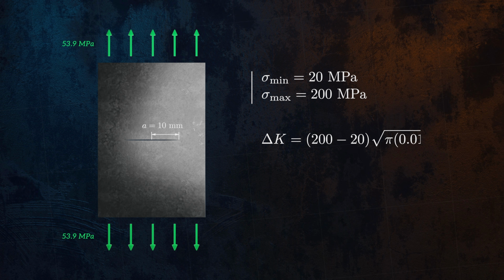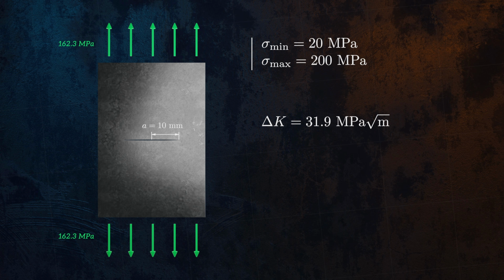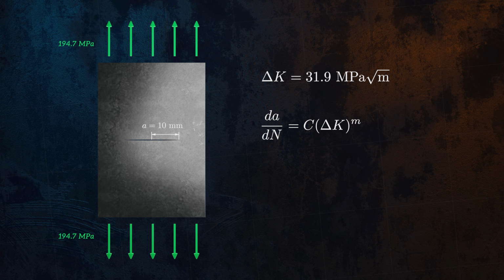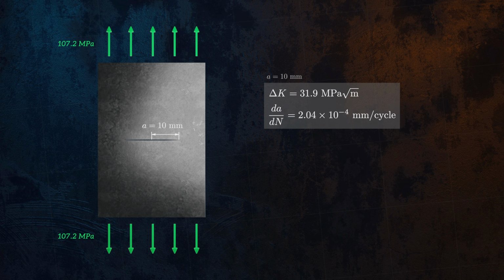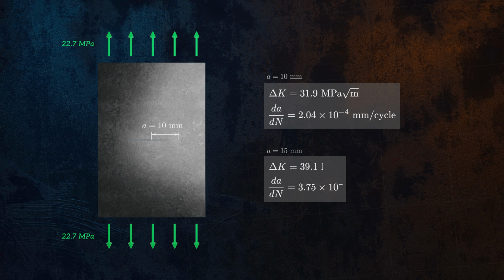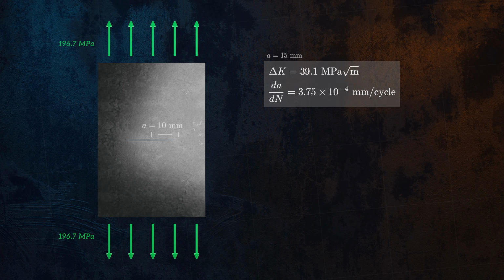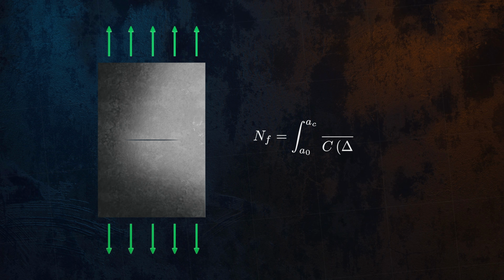Assuming material parameters that are typical for a high-strength steel, the crack will grow by around 0.2 mm every 1,000 cycles. The growth rate accelerates as the crack lengthens, though. When it reaches 15 mm, for example, the crack will have a larger stress intensity factor range, and so an increased growth rate. To calculate the total fatigue life, Paris's law needs to be integrated over the full range of crack sizes, all the way up to the critical size.